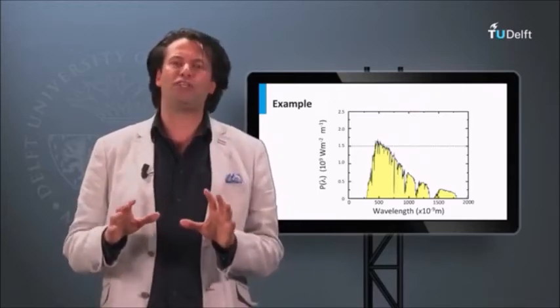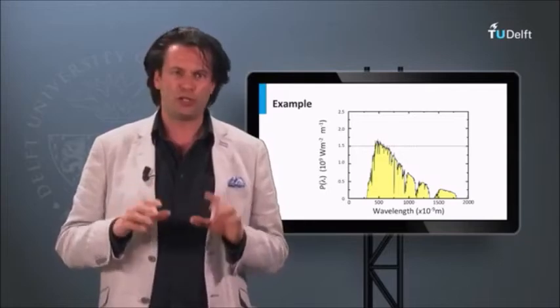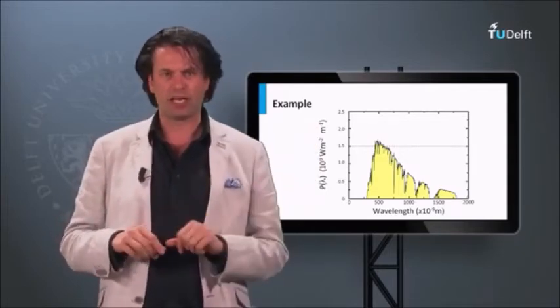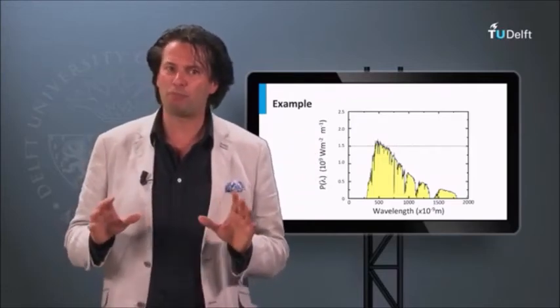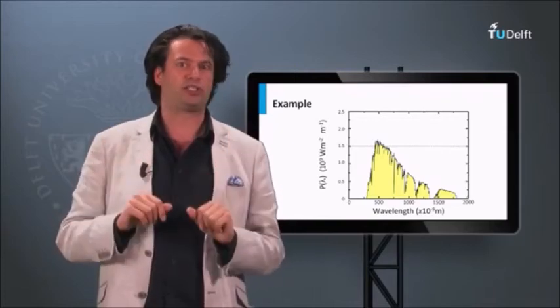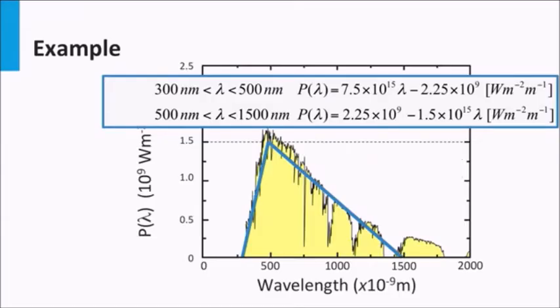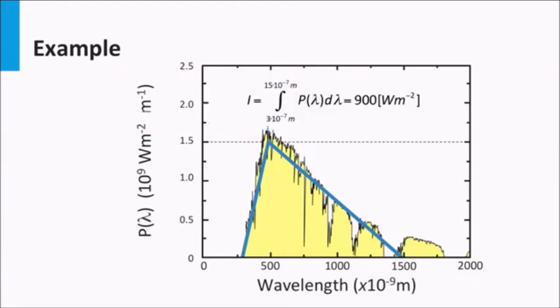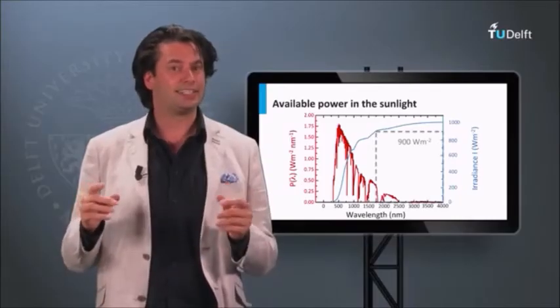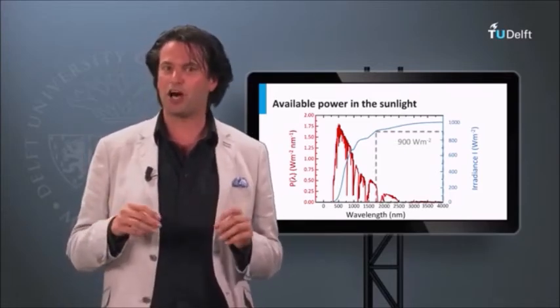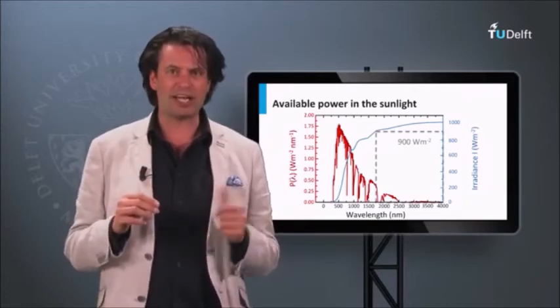I will show you an example of an easy way to estimate the current density using a simple approximation of the solar spectrum. Here we see the spectral power density of an AM1.5 solar spectrum. I will make a crude simplification. The spectral power density function of a solar spectrum can be roughly approximated with a linearly increasing line from 300 up to 500 nanometers and a linearly decreasing line from 500 nanometers up to 1500 nanometers. As discussed in week 1, the area under this triangular shaped spectrum represents the irradiance, which for this case is 900 watts per square meter. This is an excellent agreement with the real value for the irradiance up to 1500 nanometers, determined from the real AM1.5 spectrum.